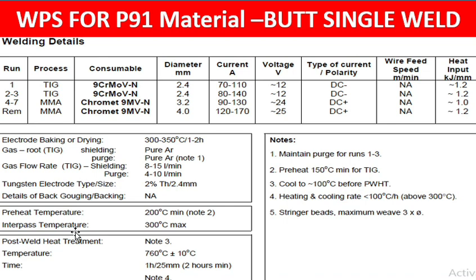Post-weld heat treatment, note 3, what is mentioned: cool to 100 degrees centigrade before PWHT. So before PWHT, you have to cool to 100 degrees centigrade. Temperature is 760 degrees centigrade plus or minus 10. We have to use that as the final temperature for post-weld heat treatment. Time is 1 hour per 25 mm minimum, so 2 hours minimum is required.